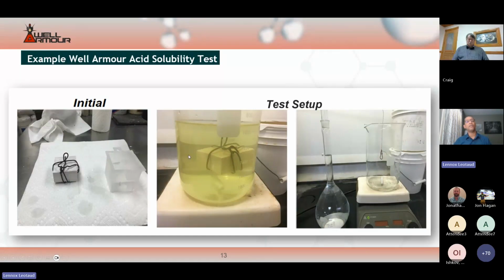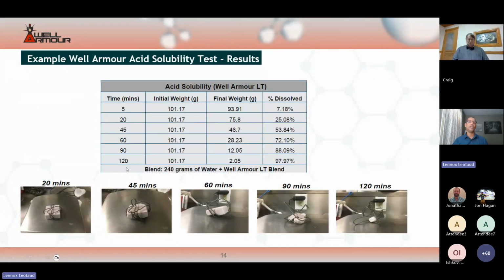This is an example of the acid solubility of the Well Armour system. A test was done; this is the Well Armour cube that was used for the test, and a hot plate and a magnetic stir rod was used to stir the acid for the duration of the test. This is 15% HCl. You can see that after 120 minutes, almost 98% of the Well Armour was completely dissolved. These pictures show, at particular timestamps, the amount of Well Armour that was dissolved.